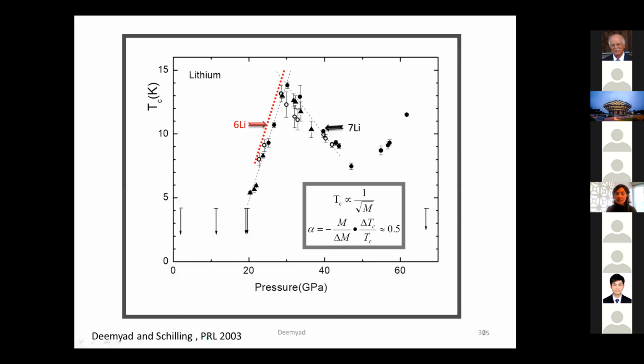Now, I'm not by any means the first one who has thought about this, and these studies have been there for a very, very long time. People have looked at the isotope effects in lithium. This is work that we have done, and one of the things that we looked at is superconductivity. And I'll tell you where I got very excited about superconductivity. This is coming from 2003 when I was working with Jim, and we measured the superconducting transition of lithium. We were one of the 3 groups that measured the superconductivity of lithium under pressure.